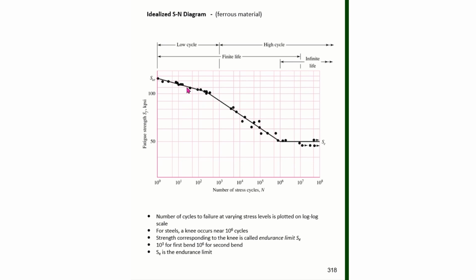Then, as the number of cycles increases, you can see that the fatigue strength continues to drop. Now, the black dots here represent experimental data. And we can see that there's a pretty good linear relationship up to just under 10 to the 3rd cycles, and that there's a constant slope. Then once we hit up in this region here, we have a steeper slope that comes down, and then here we actually go flat. So what this means is that if I were to give this particular specimen a stress of 100, I could cycle it up to this many cycles before it failed in fatigue.